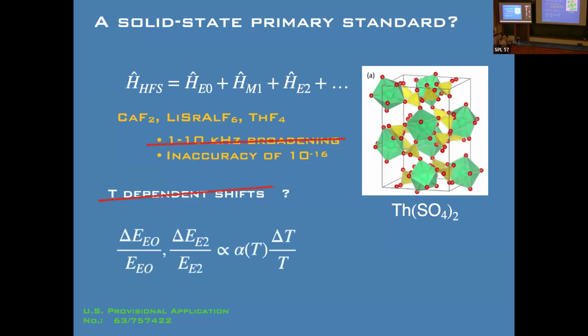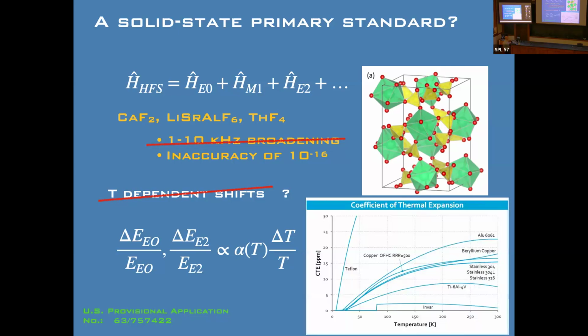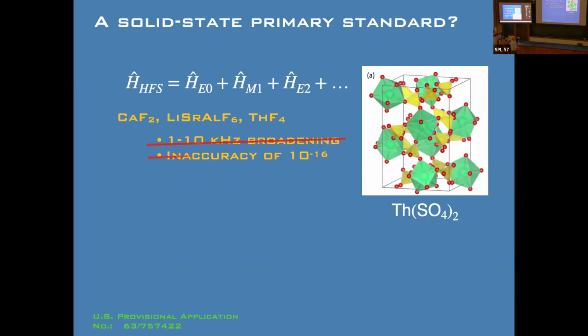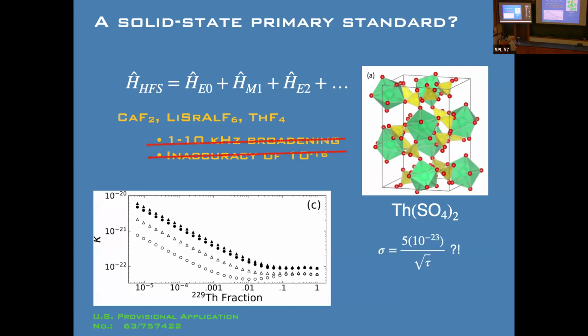And so then the question is, what can you do to get rid of these temperature-dependent shifts? We've kind of always known this, but never really worried about it. But roughly speaking, this chemical shift and the quadrupole shift, at some level, you can think of them as just being proportional to the coefficient of thermal expansion of the crystal. Like at some level, these things depend on the separation. And so it'll end up looking like alpha delta T over T, some numerical factor, right? And you guys, at least the solid state physicists, know that if you go to cold temperature, this goes to zero, right? It basically freezes out the phonons, everything becomes harmonic. And so we've been looking at this problem now, and it looks like we can get rid of this as well. And so these numbers are highly preliminary.